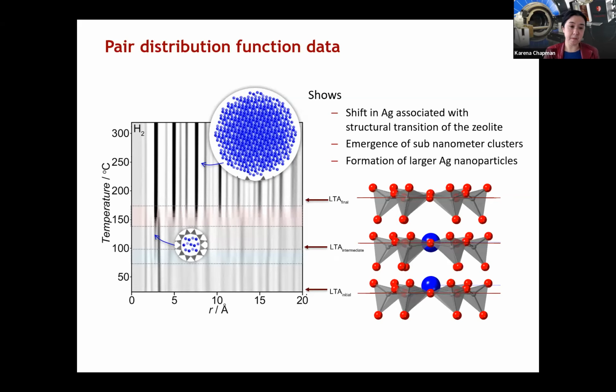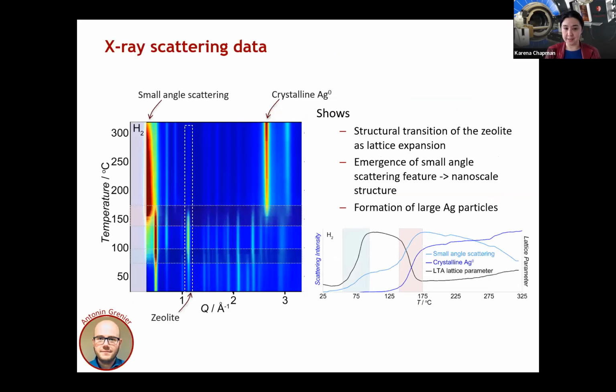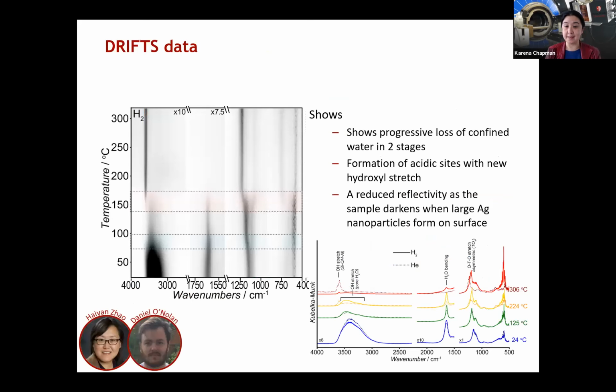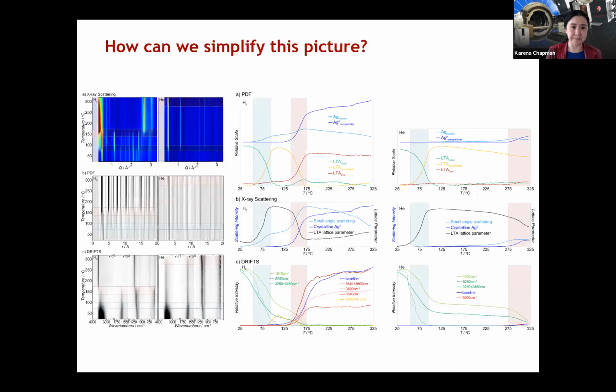So we can see this in our X-ray scattering data. We see small angle scattering that's telling us about the particles we're forming. We can see shifts in the lattice parameter of our zeolite. We can see the formation of the crystalline silver on the external surface. We have our drifts data that's telling us about the hydroxyl group and the water species that are in the pores during this reaction. And we can quantify every one of these pieces of data.